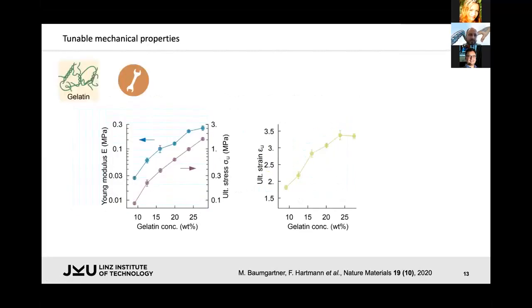But what about the mechanical properties? Again, at the base, the amount of polymer gelatin that you put in defines mostly how stiff it is and how stretchable it is. And by changing the concentration, you can vary the elastic modulus by about an order of magnitude. We are well within the range that's common for soft elastomers that are used for soft electronics and robotics. And you can also tune the ultimate stress and the ultimate strain. For these dumbbell-shaped samples, we reach about 3.5, so you can extend it by a factor of 3.5.